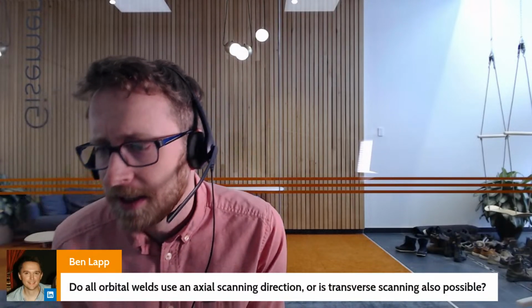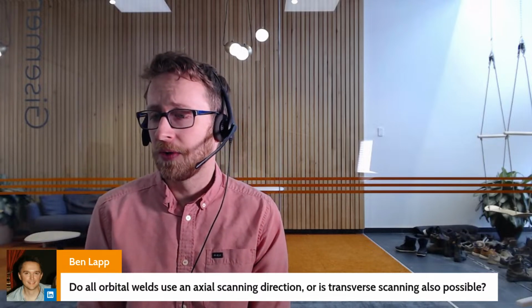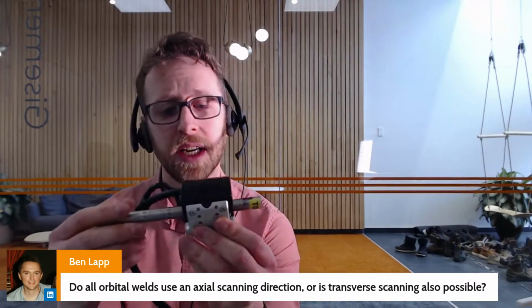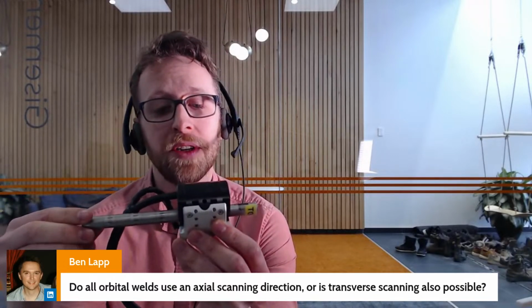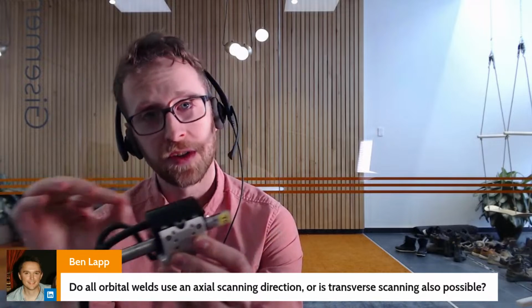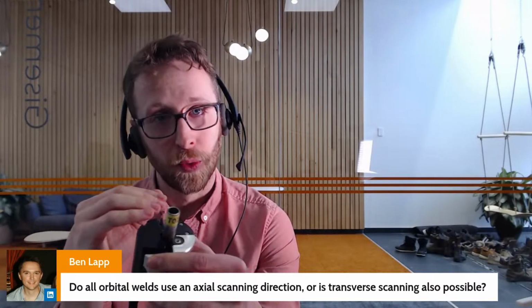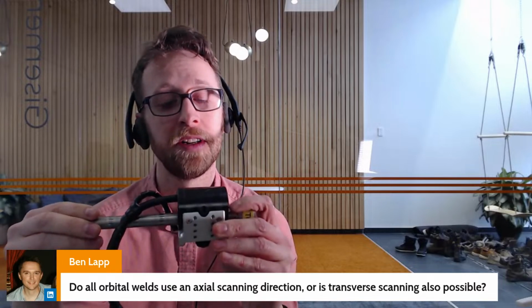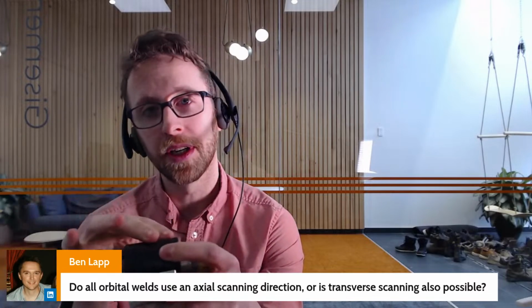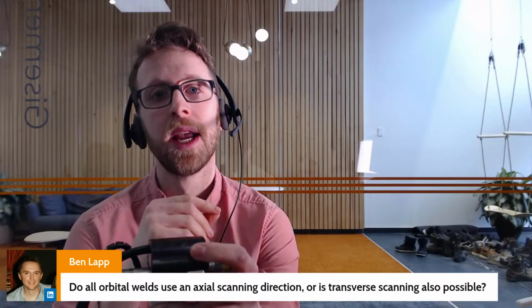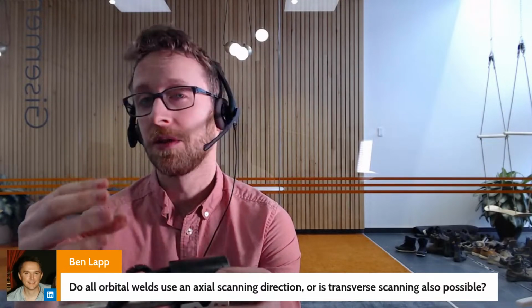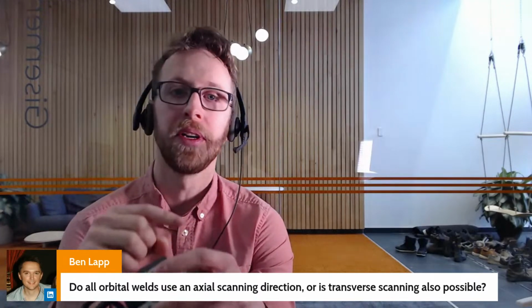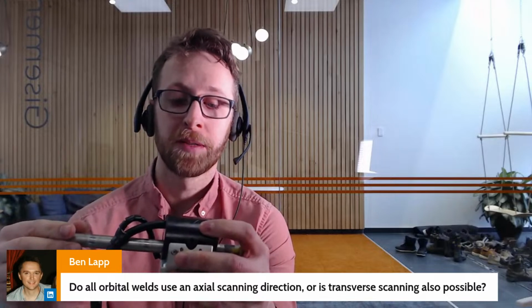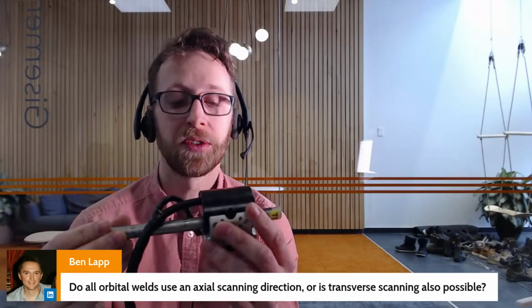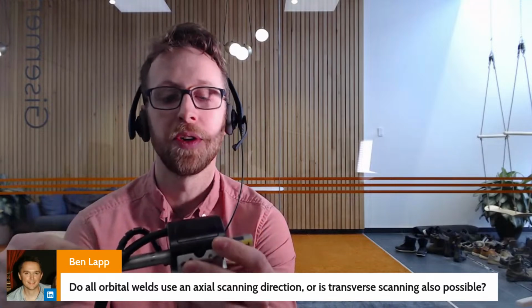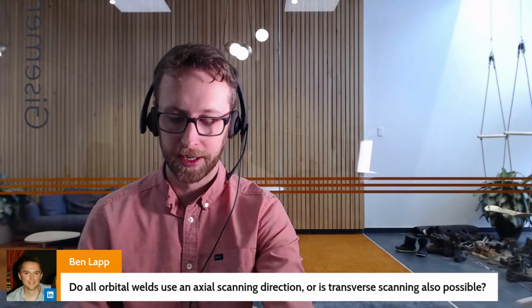Do all orbital welds use an axial scanning direction? So it is possible to use a transverse scanning, but those probes were not designed to have a transverse scanning. The scan is done axially. The main reason for that is if you're trying to do a transverse scan on an orbital weld, the weld will alter a little bit the electromagnetic properties of the material. And when you're nulling the probe, you're nulling all channels on different part of the weld. And so you're having a much better signal to noise ratio when scanning axially than when doing transverse. We did some tests. We could design a probe that does it transversely, but you get a much better signal to noise ratio doing an axial scan. So this is why we use it like that.